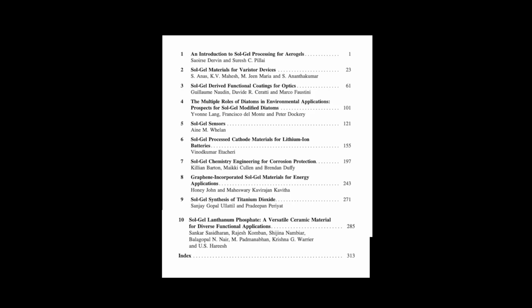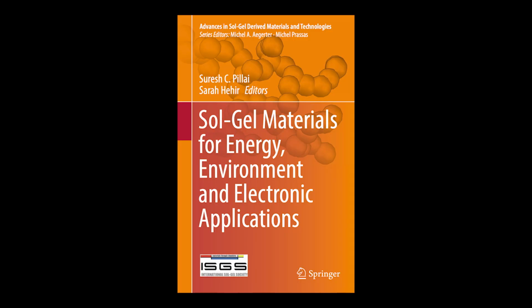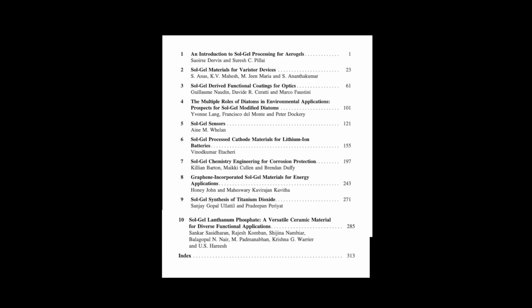The most studied and effective active inhibitors discussed in this chapter are rare earth metals with cerium salts, particularly cerium nitrate, Ce(NO3)3, being the clear frontrunner for aluminum protection. The sol-gel matrix traps these cerium ions, essentially holding them immobile and dormant until corrosion actually initiates somewhere on the metal surface. And what is the fascinating chemical trigger that suddenly releases the healing power of this trapped cerium? It sounds almost alive. It's a beautifully elegant mechanism, and it's entirely pH dependent.